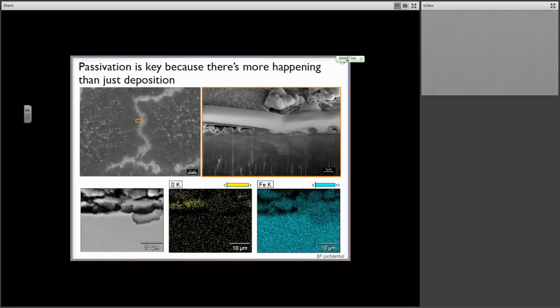But underneath, and remember, we polished this particular sample to a smoothness of less than 100 nanometers of roughness. And so all of this, that wasn't there when we started, this is all deposit material as well, except it's not necessarily just carbon-based. If we look more carefully, for example, over here in this particular example, it's almost like a bubble. And inside of that bubble is a nice little cube, which is an iron sulfide. All right? And so if we look at our EDS mapping down here, this is just the secondary electron image, we can see that we do in fact have a lot of sulfur in the deposit, but more importantly, we also have iron in the deposit.